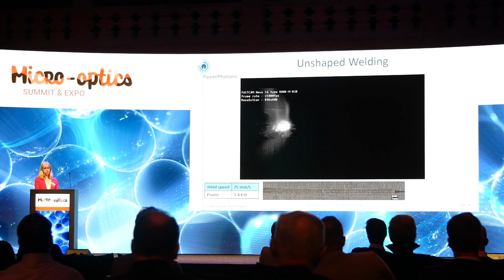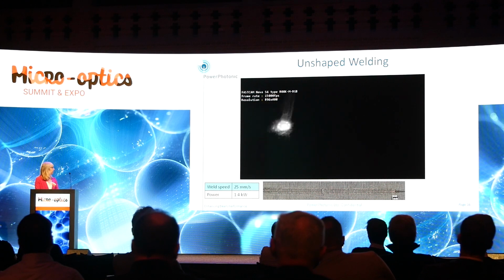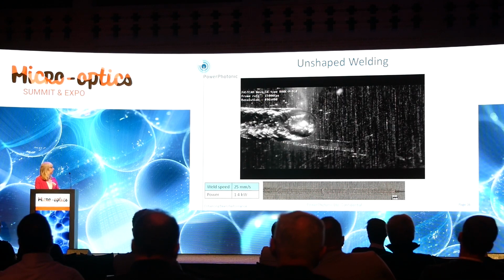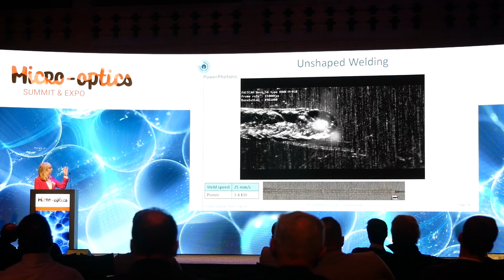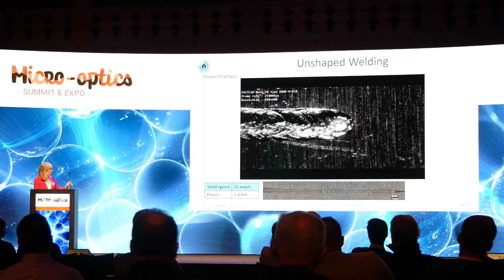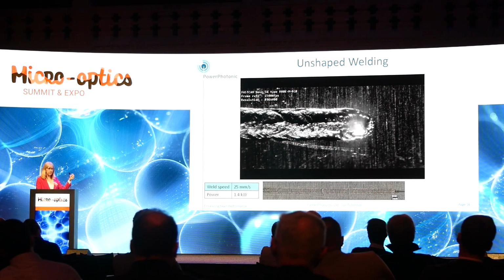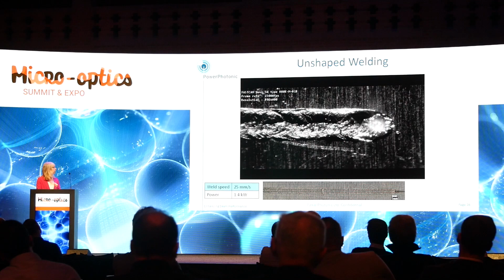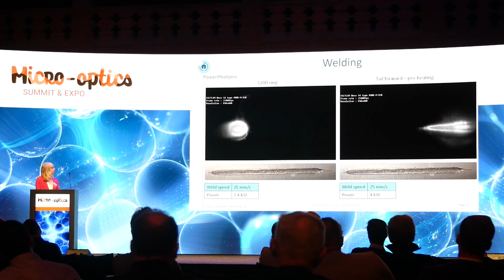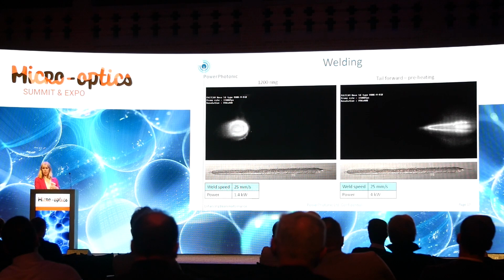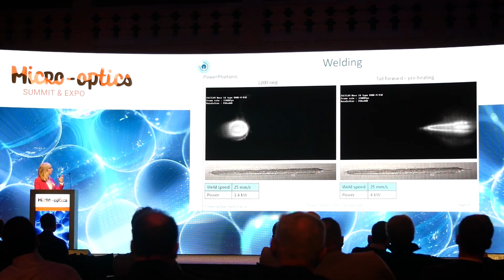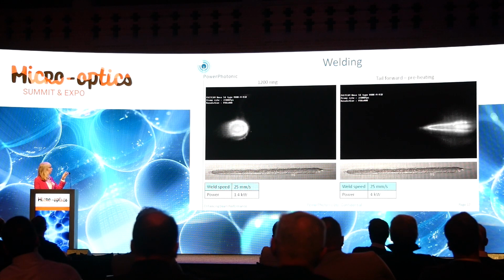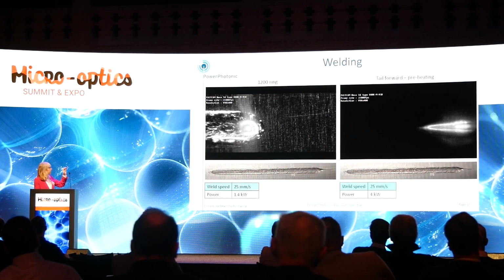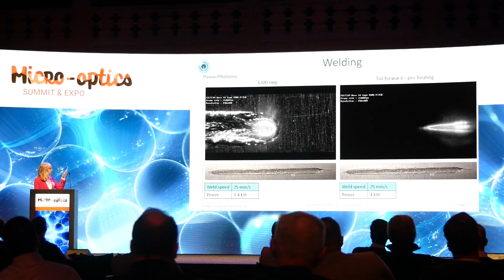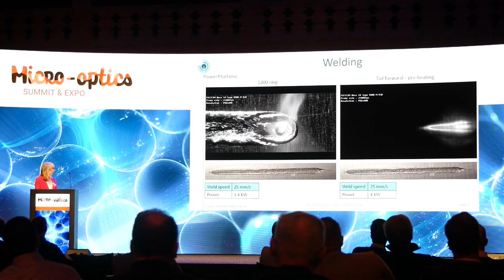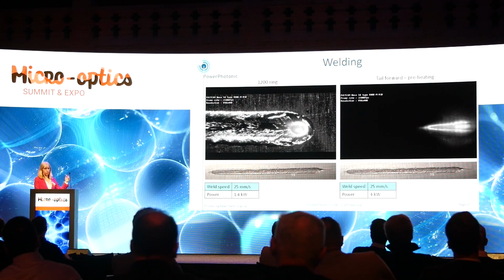So I'm going to show you a video. This is a video of the unshaped weld, and you can see that the grains are sort of less even. There's quite a lot of spatter. And in the picture along the bottom, you can see almost little lumps, and that's like air underneath. If we then move on to our beam shapers added into that unshaped spot, the first one is the ring and core. Again, you can see the grains are much more even. There's a lot less spatter. There is still a little bit of this, but it's a lot more even. And you can actually see on the picture below, there's none of those lumps.